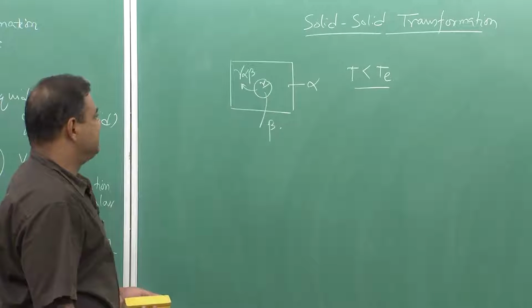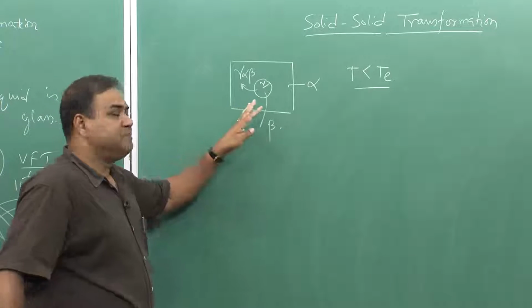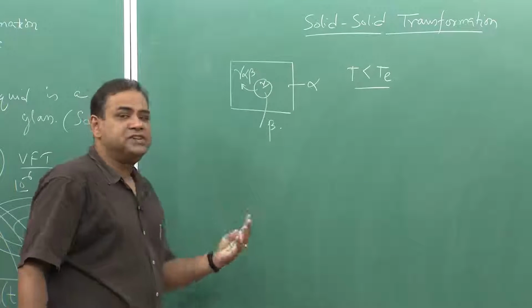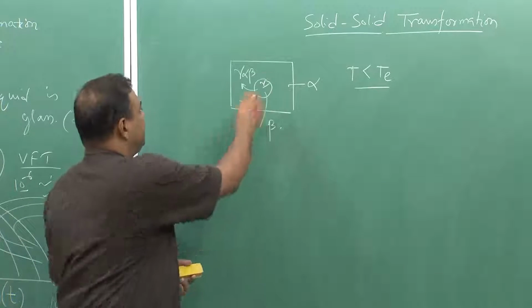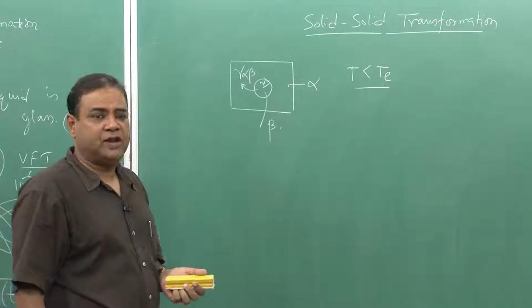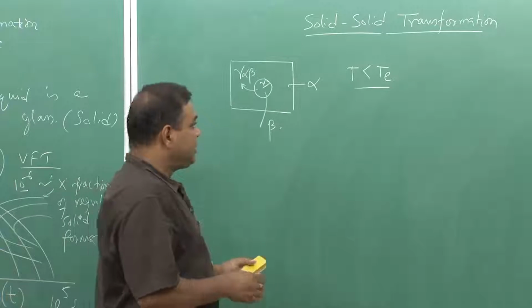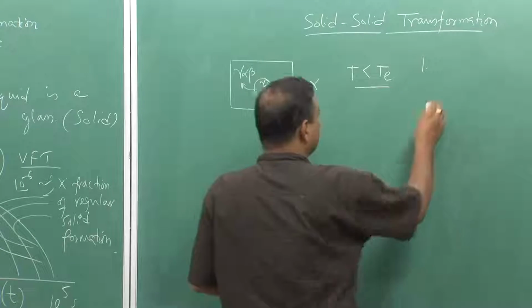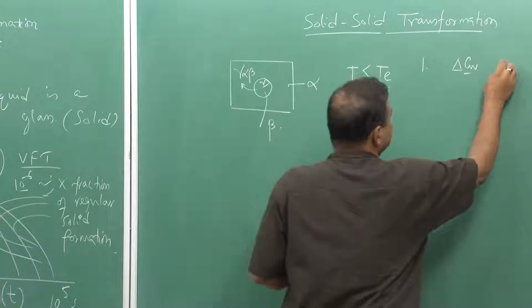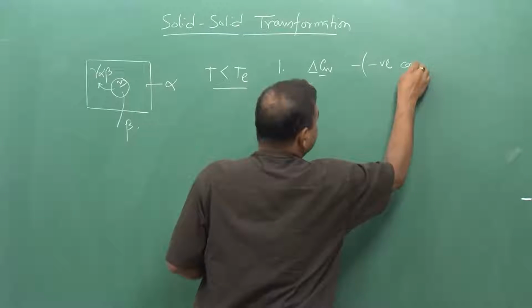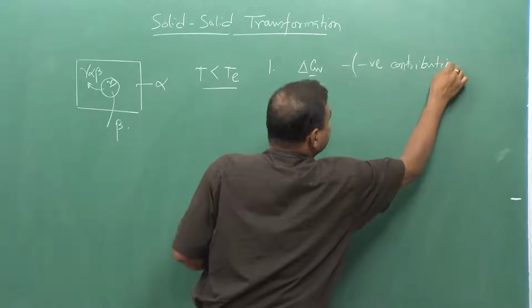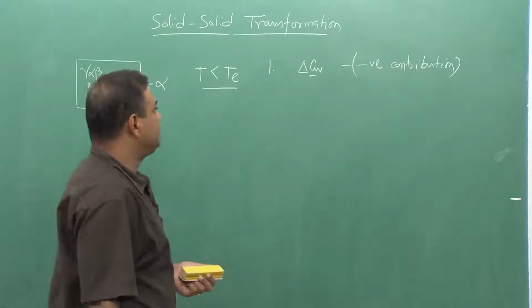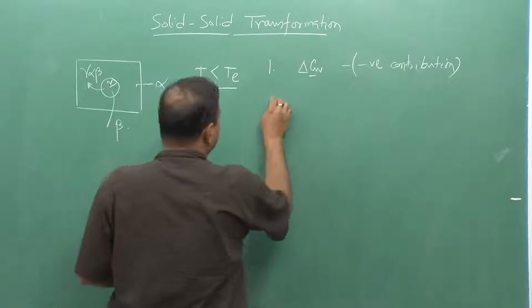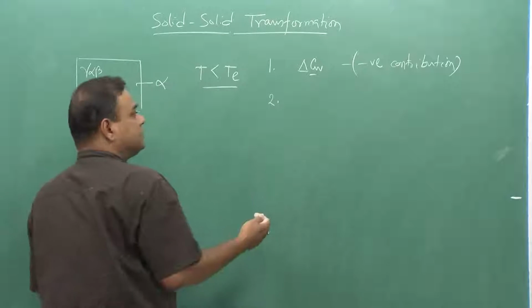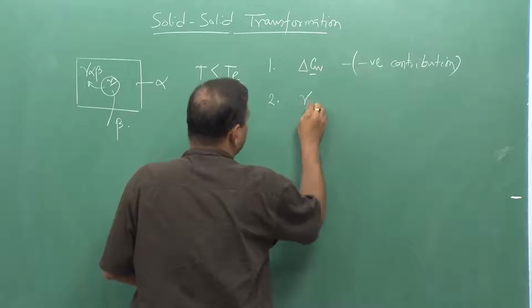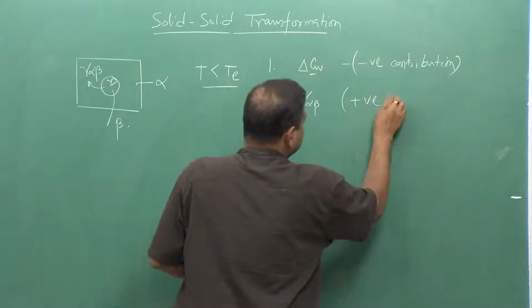Now, what are the energy terms? And here also in the beginning we are not considering volume change. This volume is the same as before, and there is no net volume change. Now, if I try to see the energy contributions, one is of course delta GV, which is a negative contribution, as we have seen in case of solid-liquid transformation. Now, the second part, which is free energy in joule per unit volume, second part, of course, is gamma alpha beta, which is a positive contribution.